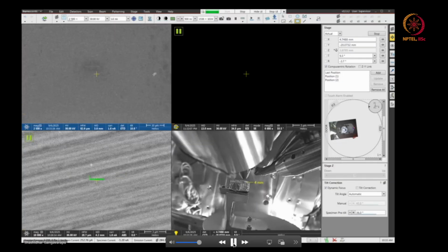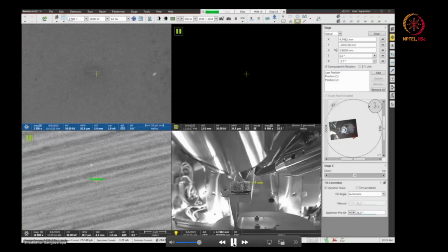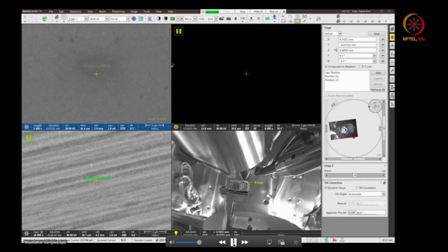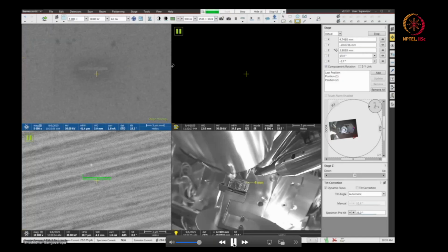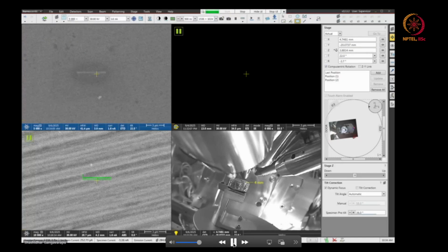So 3.88 mm is now the eucentric height. Initially we set it at 4, but 4 is not the eucentric position, so 3.8 is the eucentric now. Now again I have to tilt to 22 degrees. For APT sample preparation, we generally tilt our sample to 22 degrees. Now you can see the feature is nicely visible in the E-beam.